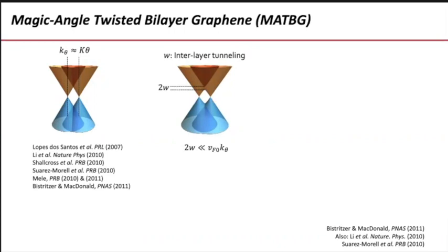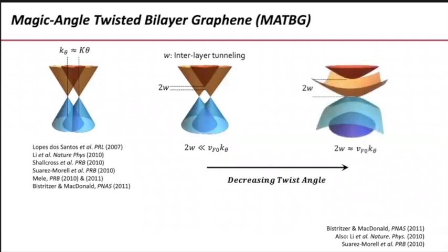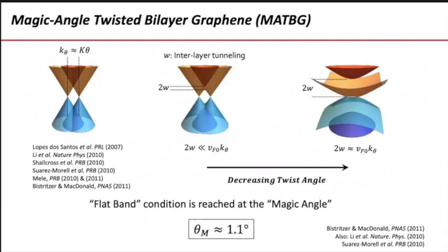Now, if you decrease the twist angle further, this was already a small twist angle, but if you decrease it further, this band, which gets pushed down a little bit by the opening of the band gap there, gets pushed down further and further until, for a certain angle, it touches zero. It becomes a flat band. This flat band condition is reached at an angle, which was coined by Bistritzer and MacDonald as the magic angle, and depends on this interlayer tunneling. And for graphene on top of graphene, at ambient pressure, it is 1.1 degrees.